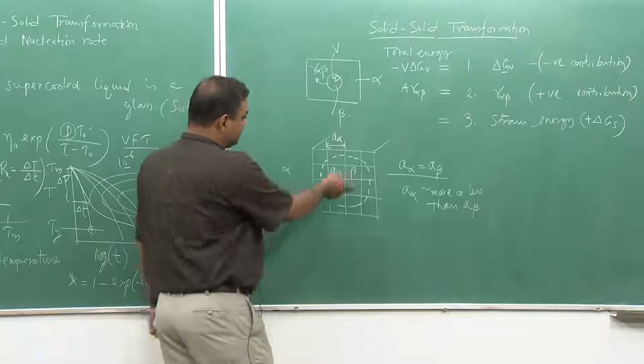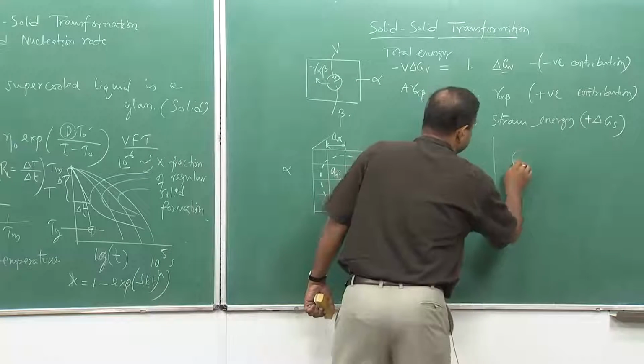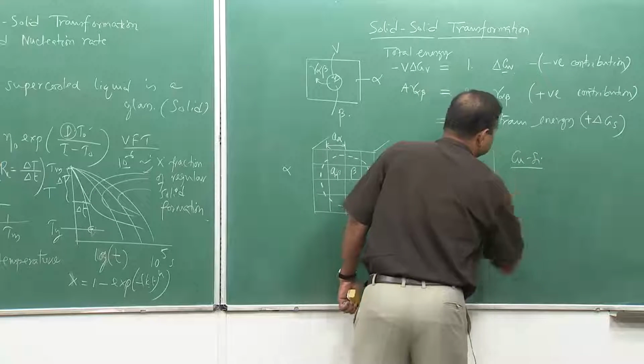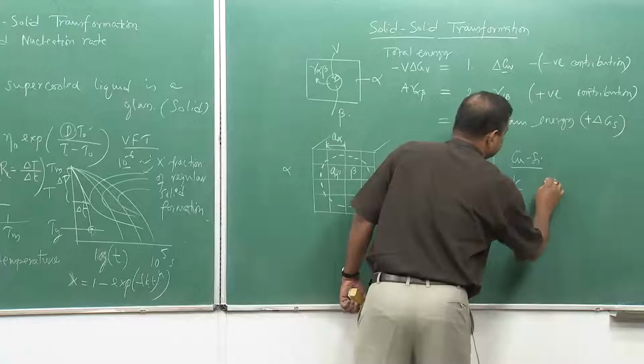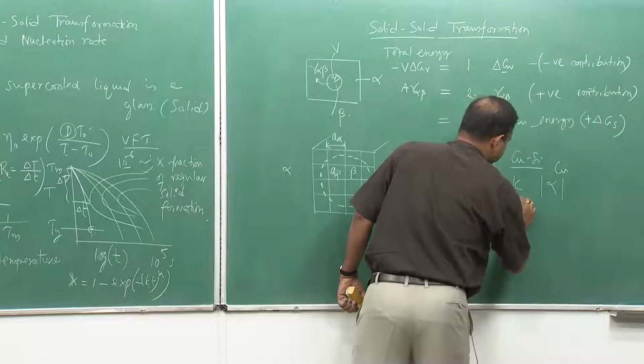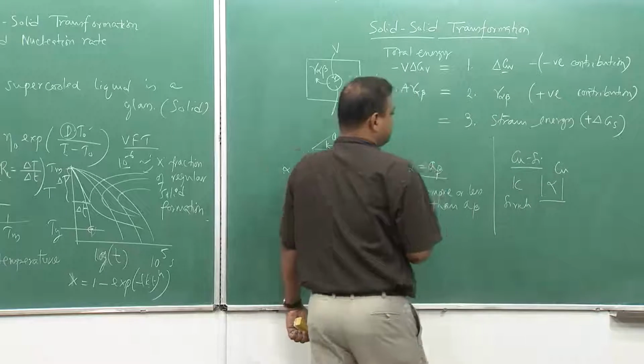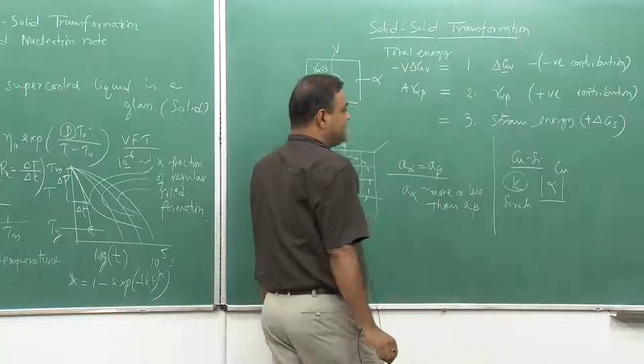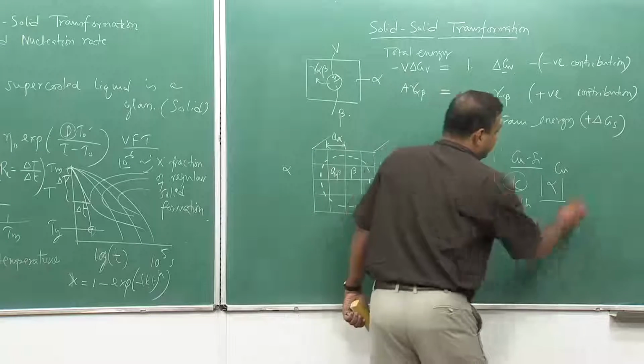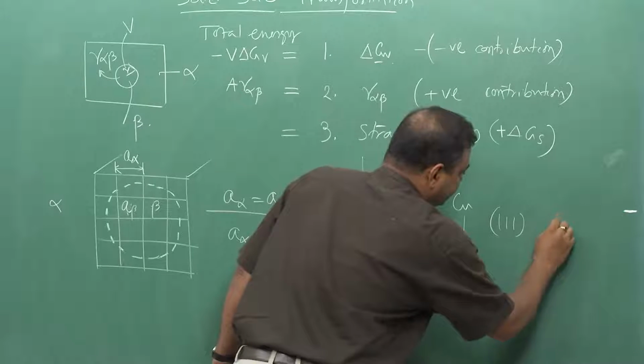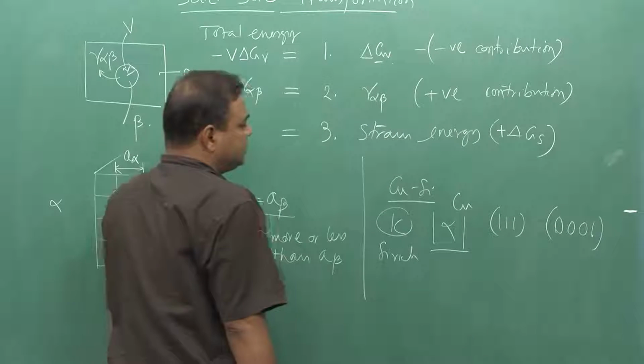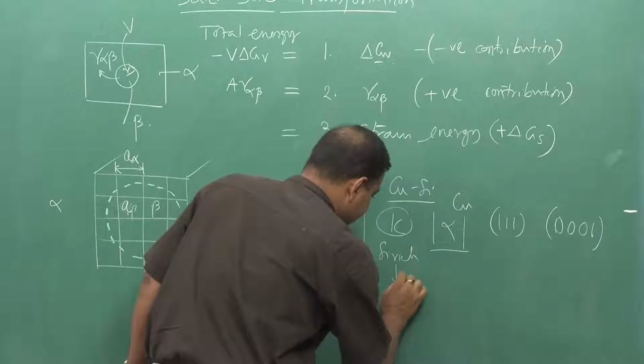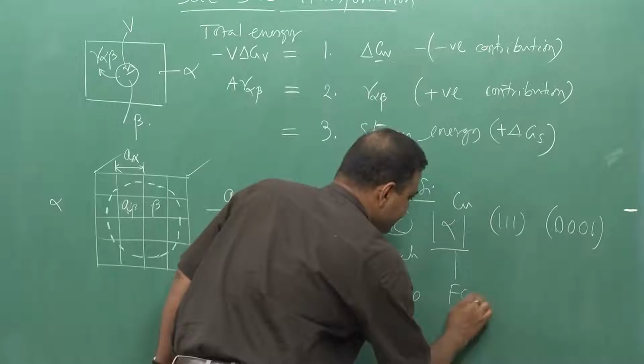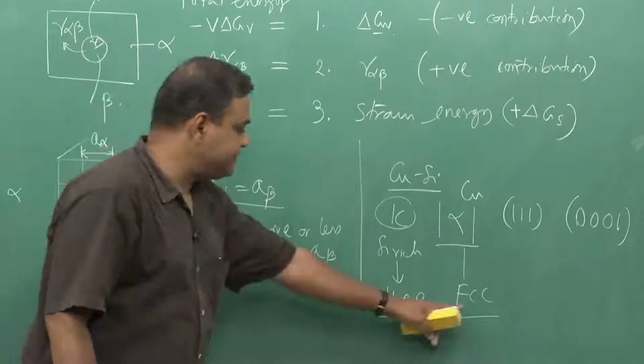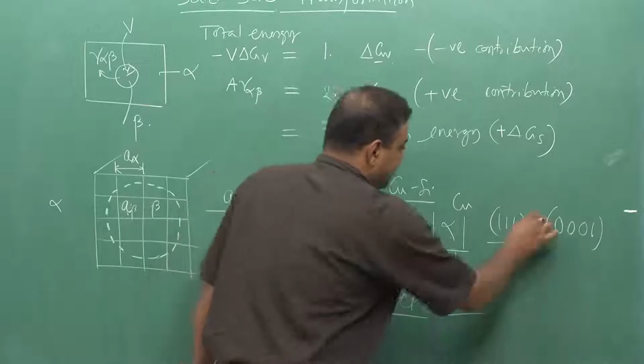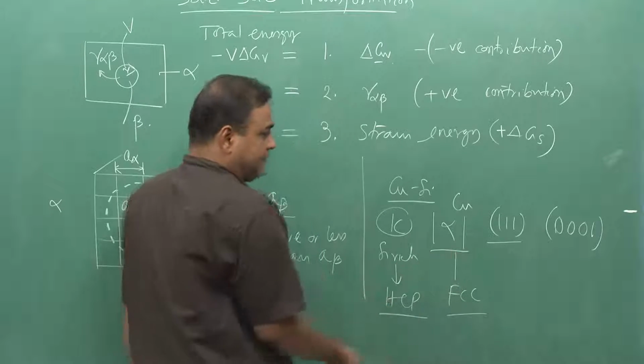For example, if we try to see one particular example, let us say in case of copper silicon alloy, we form a silicon rich phase, which is kappa phase, and the copper phase is alpha. This is copper, and this is silicon rich, and this is copper, this is alpha, which is the base, the parent phase, and this is the product phase if it forms. So we have the 1 1 1 plane as well as the 0 0 0 1 plane for these two planes of this particular crystal, because this phase is HCP and this one is FCC. So this is hexagonal close packed and this is face centered cubic. So this particular plane and the plane of this HCP, which is the basal plane, are parallel.